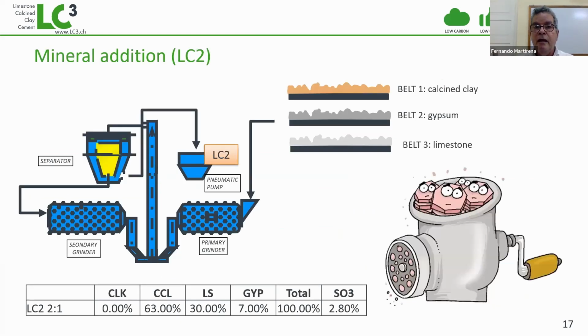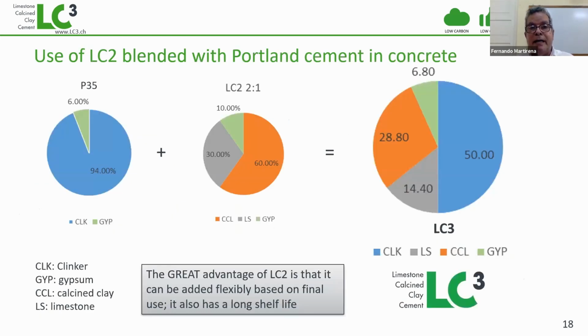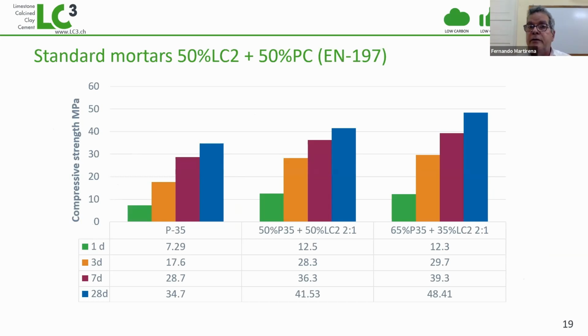concrete. We have accumulated some industrial experience producing what we call the LC2, because here we have a mineral addition that has calcined clay, limestone, and gypsum, so it's properly sulfated. And you can use it very flexibly by blending this with a cement that is available in the market. And at the level of the mixer, you have a composition of the binder similar to the composition of the LC3. And to our surprise, when we compare here, for instance, we see that the first graph is the Portland cement along the strength. And here is when you take half of this Portland cement, 50%, and 50% of the mineral addition, you see that you're even outperforming Portland cement by adding this.